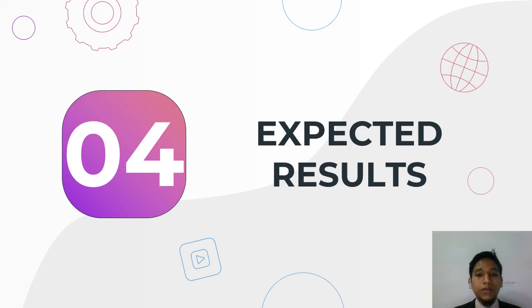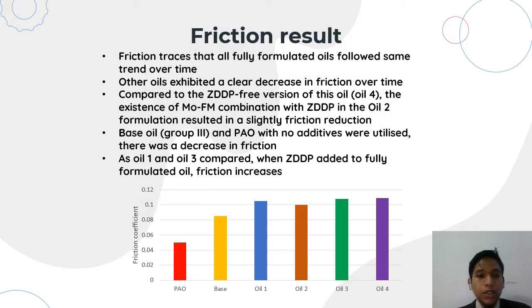Expected results. Friction result. From friction traces with respect to time from previous investigation, it can be observed that all fully formulated oils followed the same trend over time. The other oils exhibited a clear decrease in friction over time. The figure below shows the expected mean of steady state friction coefficient values for the last 1 hour compared to the ZDDP free version of this oil, which is oil 4.